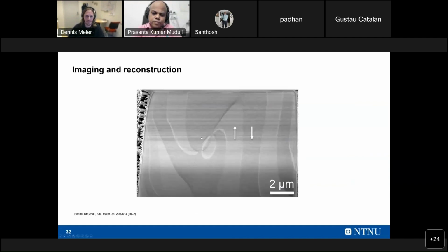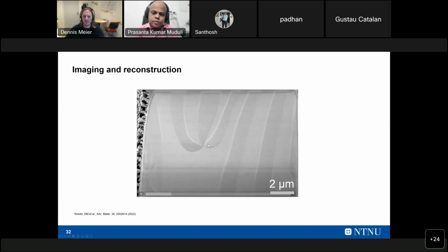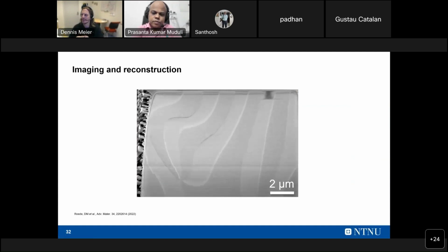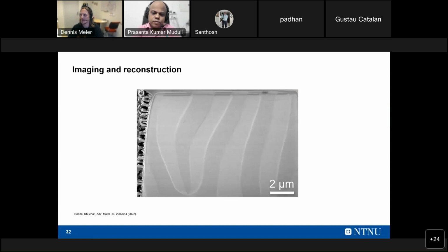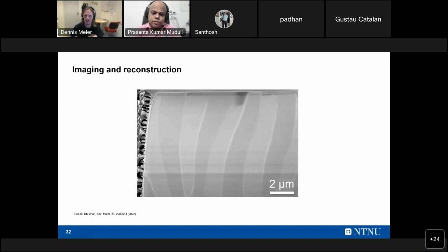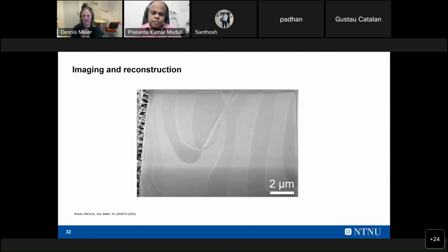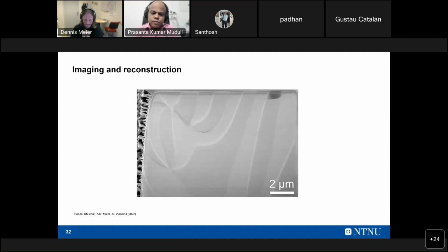And that really works. What you see here is now an SEM image on a non-polar surface of erbium manganite. So the polarization is lying in the plane, and you see what we've seen before, these meeting points. And now we are milling through the material step by step, and you get an impression of the 3D structure of the domain walls. So that's now exactly what I mentioned before. You cut and slice, and thereby, maybe we can do that again, cut and slice and get now a 3D impression of what's going on here.